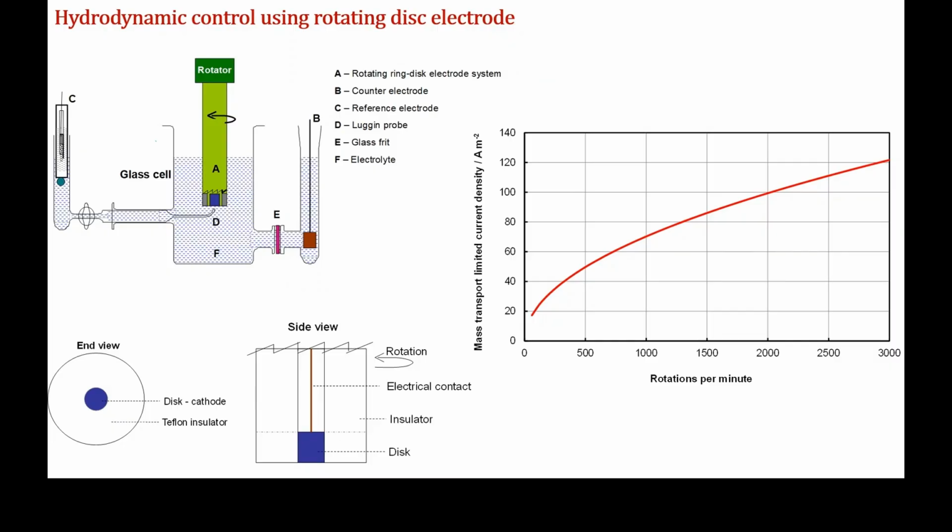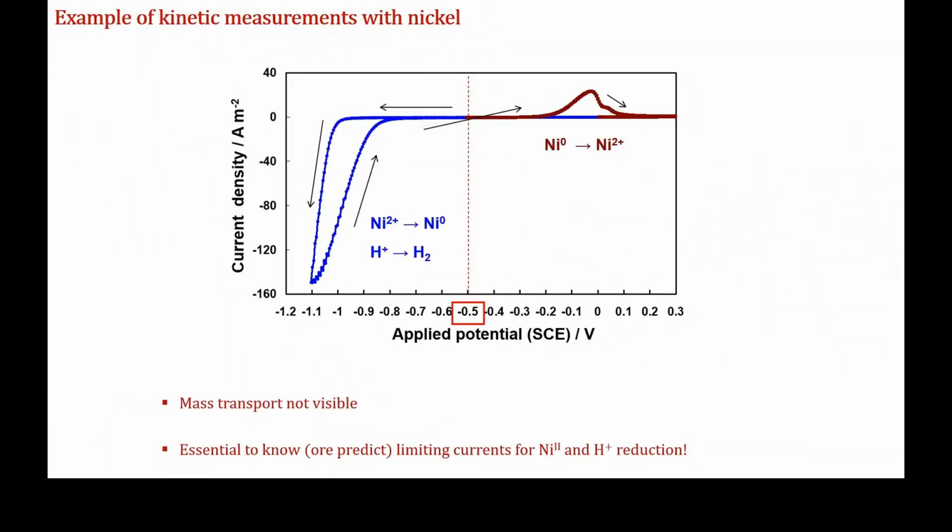So this is all nice and well, but this is what happens, for example, when I did this experiment with my nickel solution. This is one of my earliest measurements. You can even see there's some noise in there. I calculated where the Nernst potential should be for my system, for a particular concentration of nickel, at about minus 0.5 volts. SCE stands for saturated calomel electrode, which isn't sold anymore because it's got mercury in it, but they were awfully nice. In fact, if anyone knows where we can source a calomel electrode, please put it in the chat.